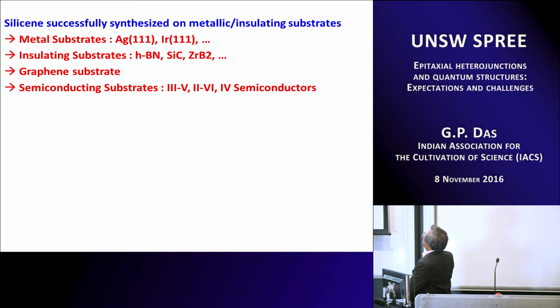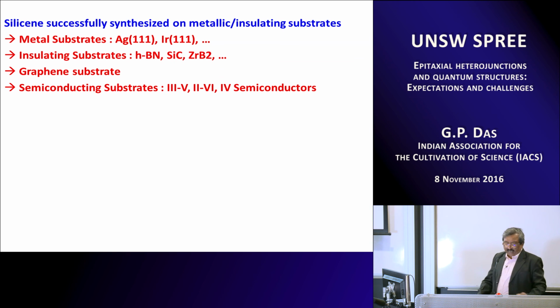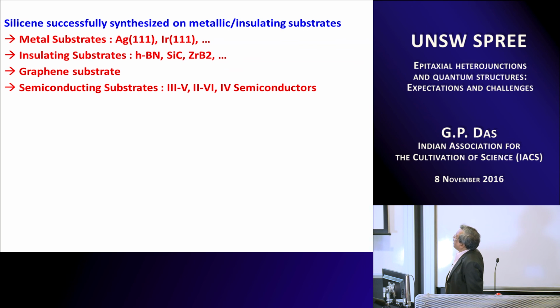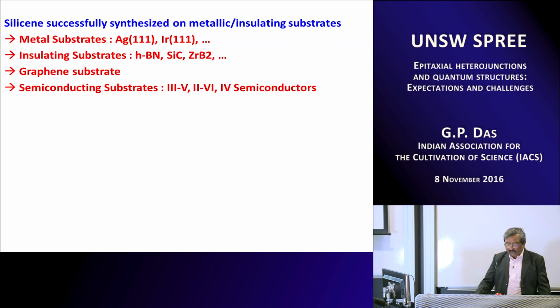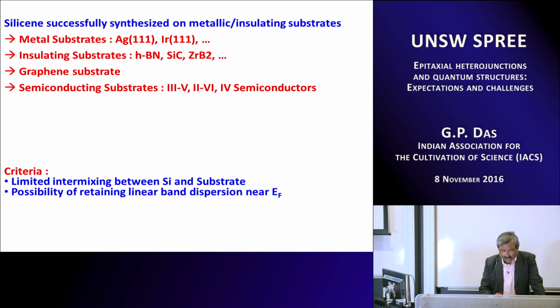Silicene has been successfully synthesized on different kinds of metallic and insulating substrates. Metallic substrates which have been tried upon are silver 111, maximum work has been done on this, also on iridium 111. And insulating substrates that have been tried are hexagonal boron nitride, silicon carbide, zirconium diboride, and so on and so forth. Graphene substrate has also been tried upon, but I am going to tell you about the last one, namely the semiconducting substrates, which is either III-V or II-VI semiconductor.